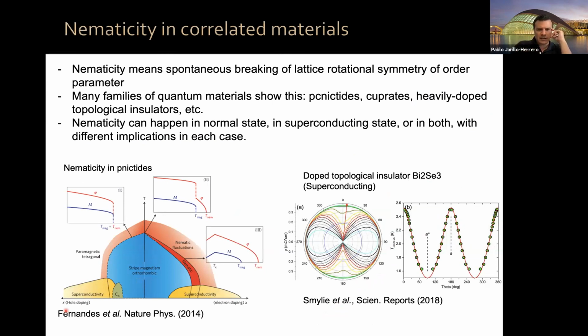In the pnictides, it has been very heavily studied in the normal state. For example, this is the phase diagram taken from the review by Rafael Fernandes. Temperature versus doping, this is electron doping, this is hole doping, and you have these regions here of nematicity in the normal state. So breaking of lattice rotational symmetry in the normal state with nematic fluctuations above, and all kinds of very interesting behavior.